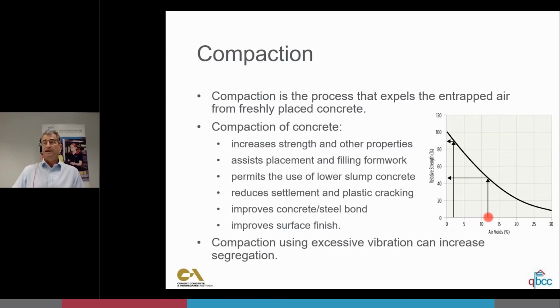But if we don't compact, if we don't vibrate, and we have the air sitting at 10 or 12%, look what happens to the strength. It's only sitting at sort of 40 or 50%. So if I order 25 MPa concrete and I don't do any compaction, there's a good chance I'm only going to end up with 12, 13, 14 MPa concrete on the ground.